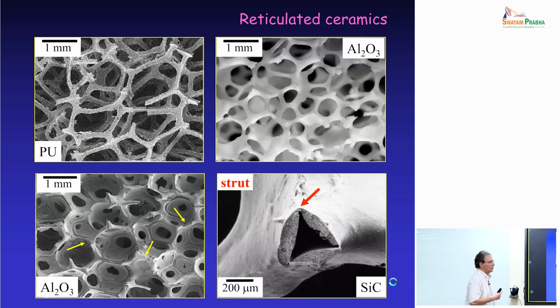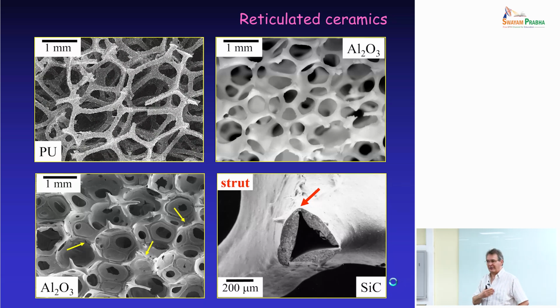Of course, these are single-use parts and need to be cheap, and that is why people don't make them using additive manufacturing for this specific application. On another point, the fact that you have a stochastic, disordered structure with different cell sizes is actually favorable for this application, because you have a flow that is more conducive to allowing particles to be attracted and attached to the foams. So the foam acts better as a filter than a regular ceramic structure.